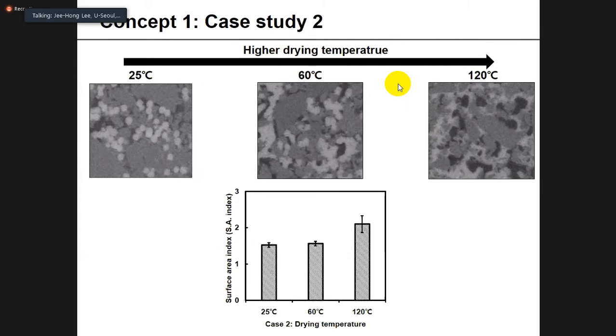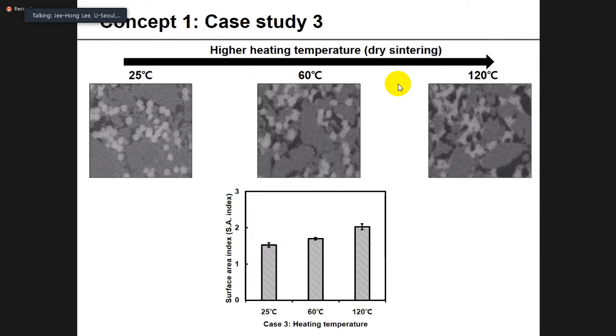The second case also shows the changes of the latex binder depending on the higher drying temperature. As the drying temperature elevates, the structure becomes more spread out and like a connected channel-like structure, and you can see that it is numerically presented with the proposed index. The third case is also similar, but the change becomes smaller because it is not treated in the wet state coating color.